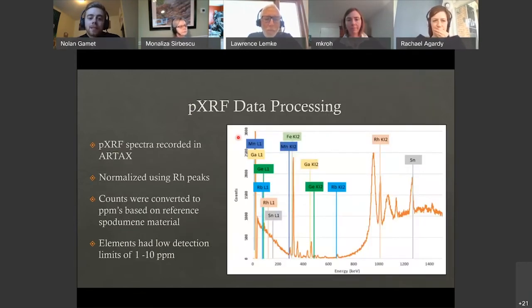For the data processing, like I said, the spectra were recorded in ARTAX. They were normalized using the rhodium peaks seen here because of the high peaks. And we used rhodium because rhodium is present in the X-ray tube of the PXRF gun. To normalize these, we used the rhodium counts in ppm and divided that by the photon counts. The resulting value was then multiplied by the element of interest's photon counts. The elements that we used had low detection limits of about 1 to 10 ppm, as seen here, this small Gaussian curve. And that's why we also excluded rubidium, because the curve was so small and under detection limits.